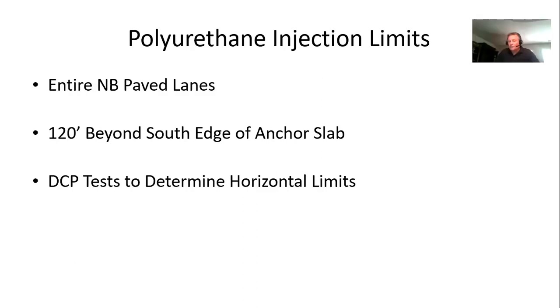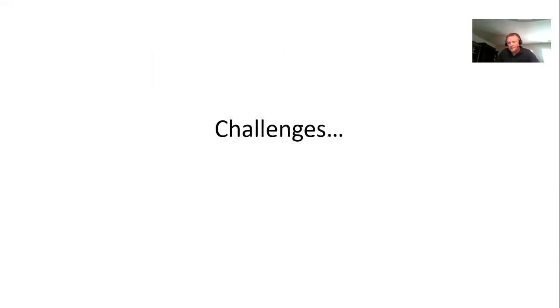Yeah, and so we use that basically to set our limits on what we wanted to inject, and then we further refined that later as they were driving the rods themselves. And then we knew we had to go deeper right near the abutments, and so I believe some of that you pre-drilled. But it was actually kind of a layer maybe where we weren't necessarily able to get down through it with the DCP, but we knew we had something soft down below, and so we also concentrated on that a bit.